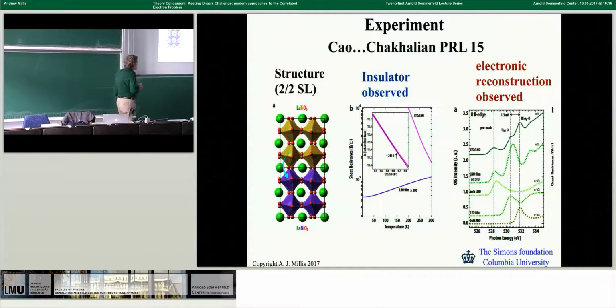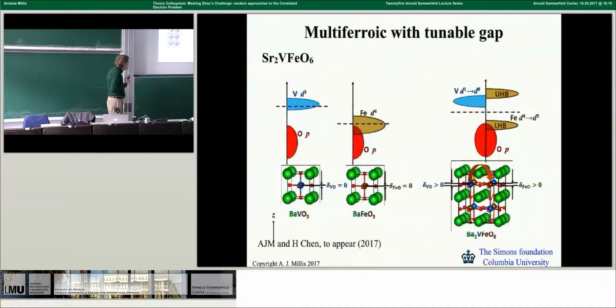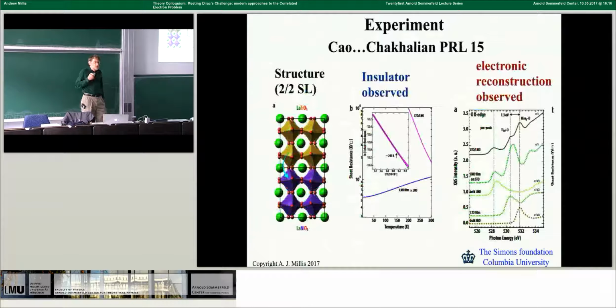Similarly, they were able to see, and I don't want to take the time to walk you through this experiment in detail, but there's a high-energy spectroscopy that probes the local electronic configurations. And what they were able to see was that in our superlattice, the electronic structure was changed. So it's neither like lanthanum titanate, which is this, nor like lanthanum nickelate, which is this, but is instead this structure, which is essentially the same as nickel oxide. So in summary, they were able to verify that the charge transfer occurred, that the electronic structure was rearranged in the way that Hanghui had predicted.